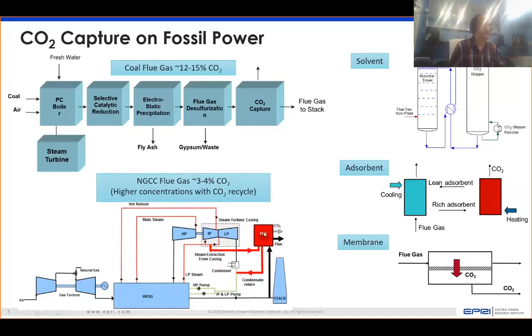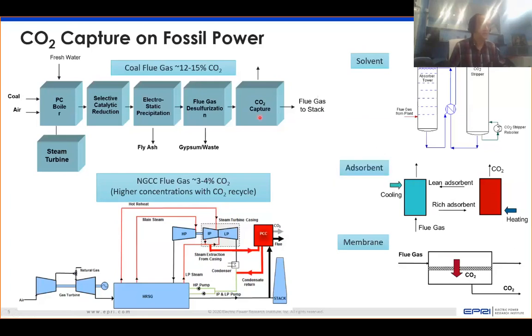But this block here of the CO2 capture can be thought of, let me get some pointers here. Yeah, so this block here of the CO2 capture block is really just another environmental control, and that has to do with a solvent-based system in which you have a CO2 selective solvent which will absorb the CO2, and then you have to remove the CO2 by heating it up. And the heat for this actually is delivered from the power plant steam cycle.